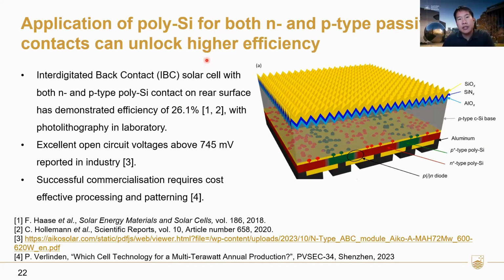So previously, we've mentioned that in the standard TOPCon structure, most of the polysilicon passivating contacts is limited to the rear surface because of absorption of light. So it's less efficient if you apply the polysilicon on both surfaces. But an alternative structure is to basically turn the device into almost a 3D structure by alternating between a p-type contact and an n-type contact, typically in a rectangle, with just alternating strips of n-type and p-type and n-type and p-type